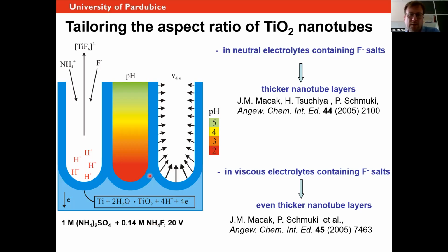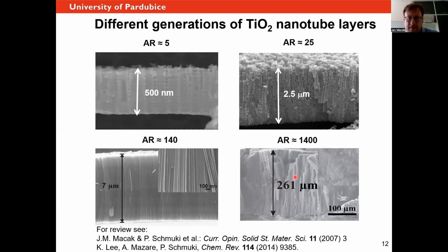And by doing so, we were able to have the acidity inside the tubes only at the spots where we needed it. So where we needed actually to drill deeper into titanium, but the tube walls were preserved simply by having higher pH there. So the titania did not readily dissolve there as it would dissolve here. But because this was neutral, these walls were preserved, and at the end, the whole nanotube layer could grow thicker. And we showed it first in the aqueous solutions, then we switched to viscous electrolytes, based on glycerol and ethylene glycol.